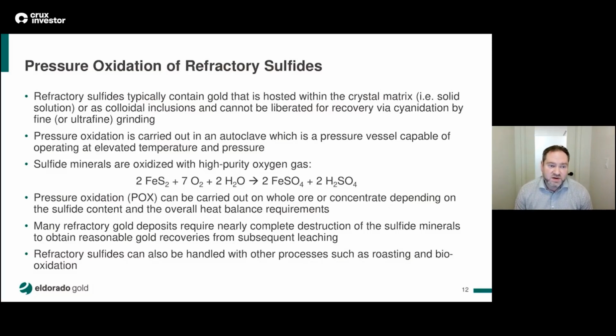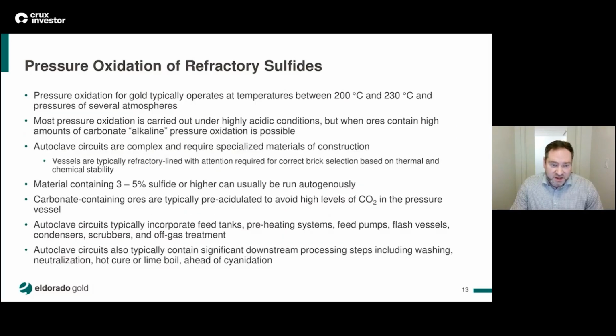So moving on quickly to pressure oxidation of refractory sulfides. Some gold, as we heard earlier, is present within the crystal matrix of the pyrites or other sulfides that are contained in the ore. And this material cannot be liberated typically by fine or ultrafine grinding. So pressure oxidation is carried out in a pressure vessel. And we typically can run this on either whole ore or concentrate. And a lot of the refractory material needs to be destroyed completely in order to get successful leaching in the subsequent downstream processing. Autoclaves are very complicated circuits.